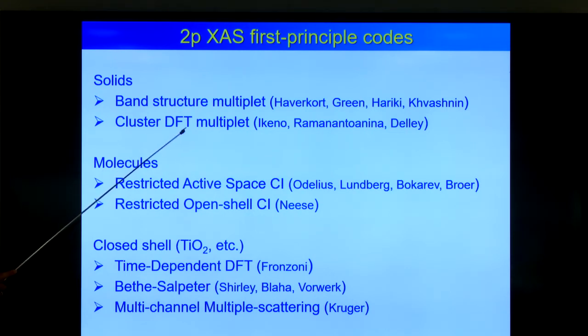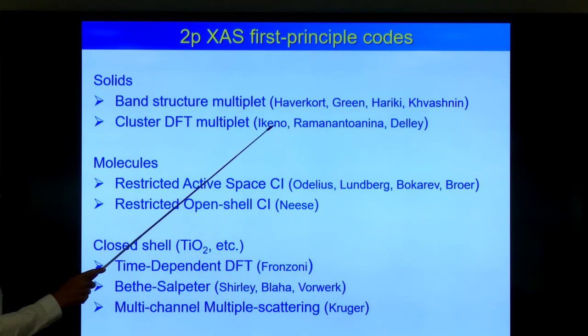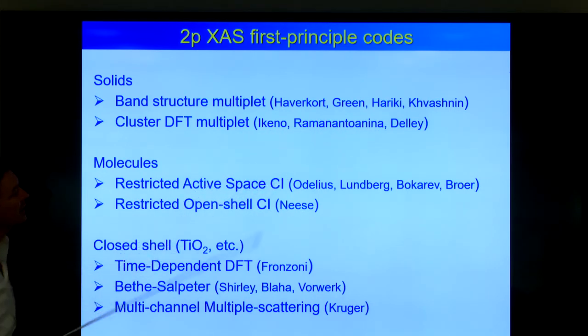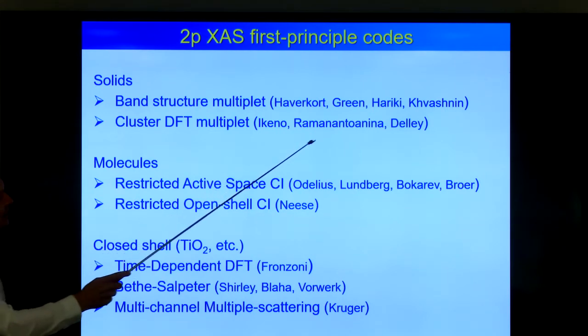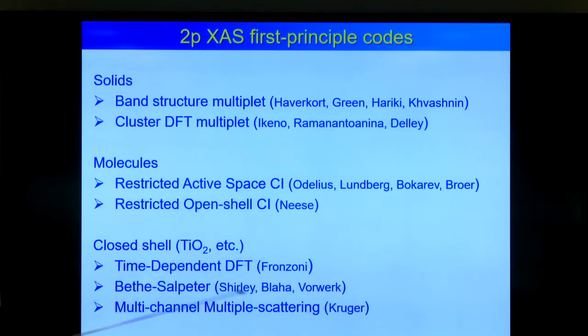You can also do everything in real space. I call that cluster density functional multiplet. That's done in Kyoto by Ikeno and by two groups in PSI. Ramanantoanina programmed the multiplet calculations into ADF, Amsterdam Density Functional, and people use that. You can just say, I want the L-edge, and you have the L-edge. And they use a cluster DFT. That's not completely ab initio because they need some guiding parameters to tune the calculation.